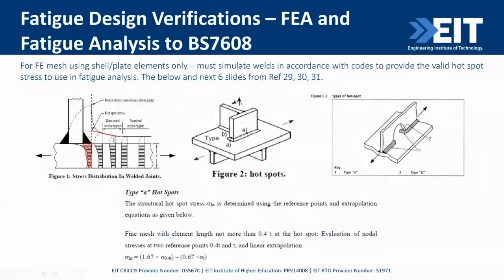What you need to do is find out your stress at 0.4T and 1T out from your weld toe, linearly extrapolate back into that as per here, and there's your hotspot stress. So you're not including the non-linear peak of the notch stress. It's this hotspot stress via this extrapolation method.